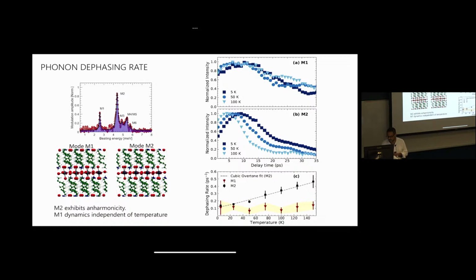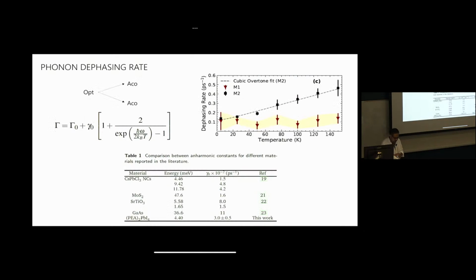And so what we see here, if you look at the temperature dependence of the coherent response from this vibrational spectroscopy, this is M2, the one that really dominates. It's highly temperature dependent, you can model it. In a minute I'll show you how. This one is not very highly temperature dependent. It's rather temperature independent. This one has slightly more out of plane motion than this one, and that could be one reason why that's the case. But you can model this as you generate an optical phonon because you've excited your carriers in the semiconductor, that you have a parametric conversion between that and acoustic phonons, and it's a nonlinear process, and you can quantify the nonlinearity by looking at this anharmonicity parameter. And so that's a very important quantitative input, and I don't have time to get more into that. There's quite a bit more to say.